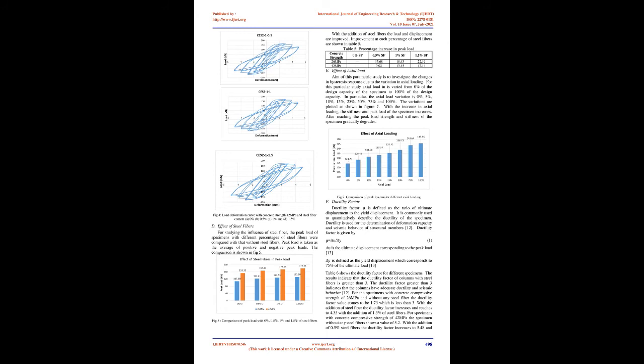D. Effect of steel fibers. For studying the influence of steel fiber, the peak load of specimens with different percentages of steel fibers were compared with that without steel fibers. Peak load is taken as the average of positive and negative peak loads. The comparison is shown in Fig. 5. With the addition of steel fibers, the load and displacement are improved. Improvement at each percentage of steel fibers is shown in Table 5.